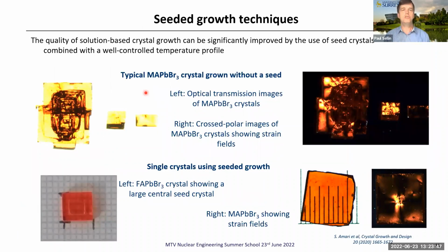Let's go back to solution-based growth. Solution-based growth can be significantly improved by the use of seed crystals. I've already alluded to the fact that spontaneous nucleation is your enemy in solution growth. You don't want random nucleating sites. So often what's done is small crystals are grown first and then they're put back into the precursor solution